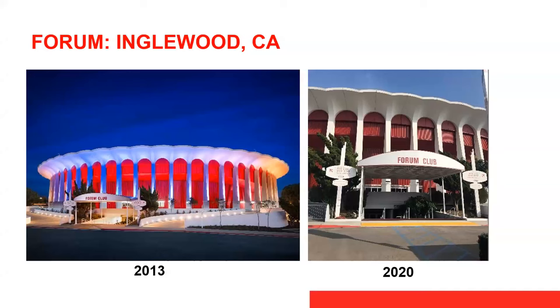Okay, so here you can see the Inglewood, California Forum. And this building is a National Historic Landmark. And they had to be really careful when it came to the exterior of the building. They wanted to make sure they found a single coating system that would protect the building for many years. On the left, it was originally coated in 2013. And in 2020, we took a photo on site. And you can see that now I'm happy to report even 10 years later that the red is holding up really good with regards to color and gloss retention after 10 years of exposure. This was coated with two coats of epoxy and then an FEVE fluoropolymer as the top coat.